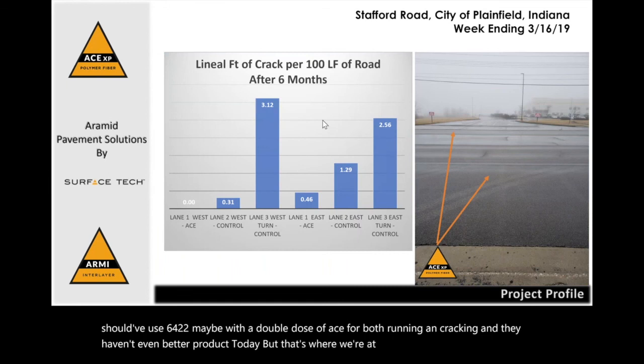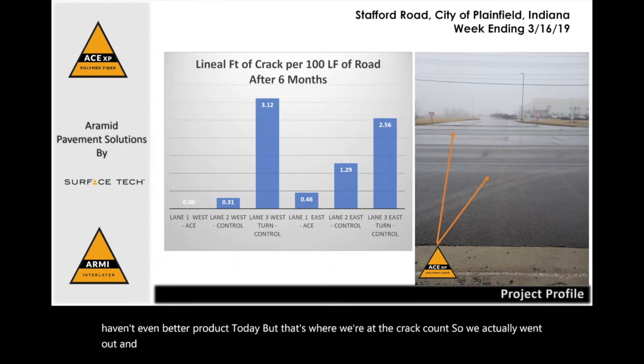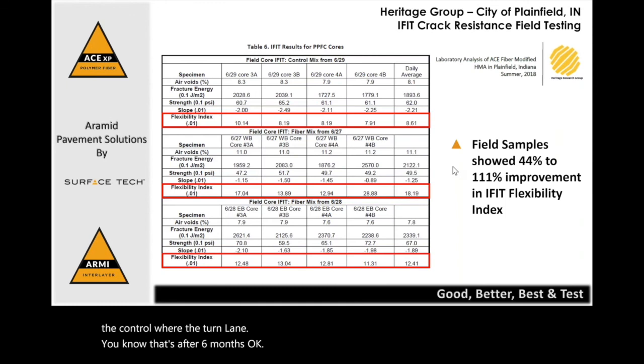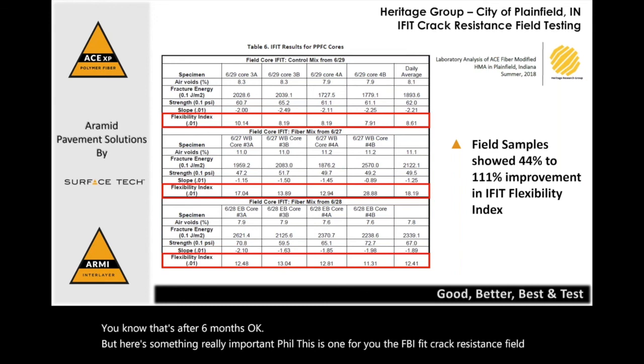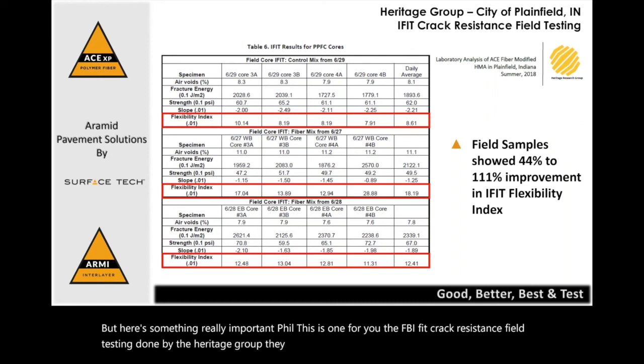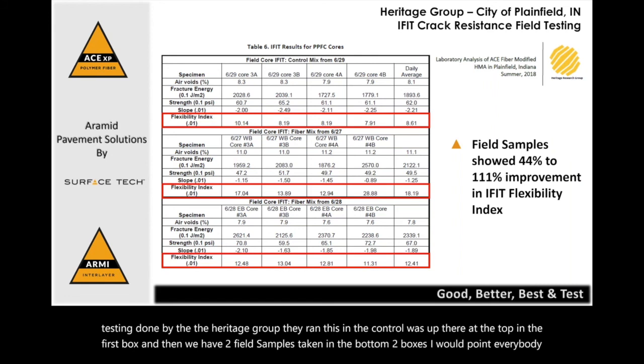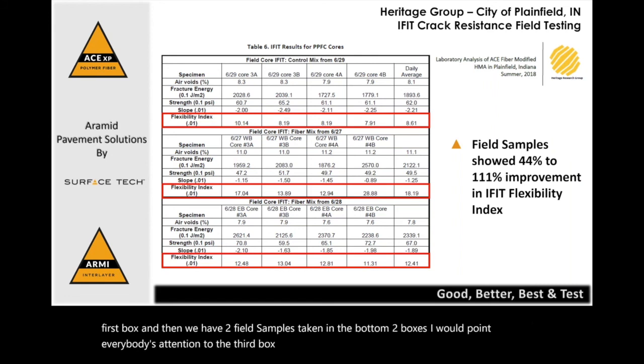The crack count, so we actually went out and counted those cracks, and as you can see, the ACE lane is just so much better than the control or the turn lane. That's after 6 months, okay? But here's something really important, Phil. This is one for you, the SCB iFit crack resistance field testing done by the Heritage Group. They ran this, and the control was up there at the top in the first box. Then we have two field samples taken in the bottom two boxes. I would point everybody's attention to the third box down and compare it to the first box.